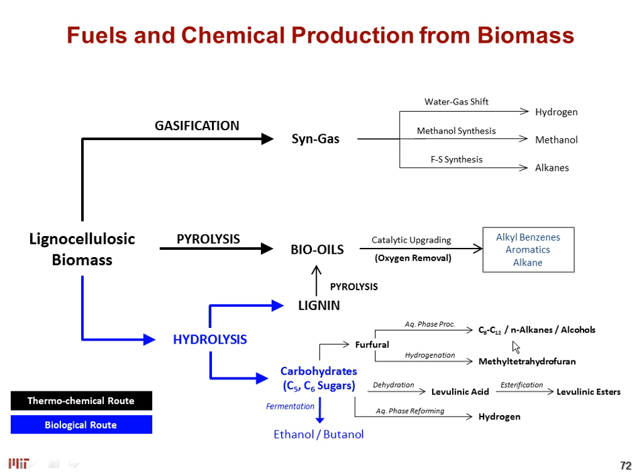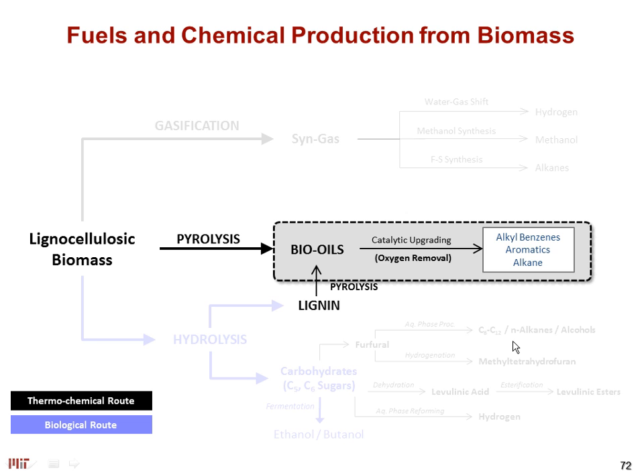that, looking at the classic pathways for biomass conversion, we look at this middle range temperature conversion pathway where you take biomass, heat it very quickly in the absence of oxygen, and pretty much liquefy it. So you produce some condensable gases, you produce some char, and then you produce what is called this bio-oil, or this soup of components that are in the liquid phase. And the challenge that we have is, how do we establish a heterogeneous catalysis scheme that will be able to deoxygenate these bio-oils and transform it into molecules that are more easily integrated with current refinery streams.